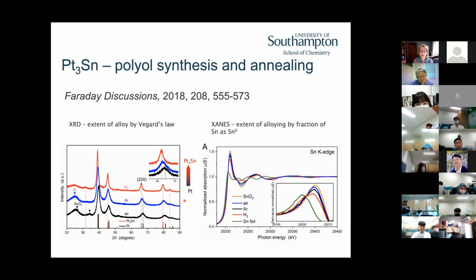If we anneal it in air, argon, or hydrogen, what we do is we exchange the extent of mixing of the materials and of the atoms in the nanoparticles, such that if you anneal them in air, the sample looks very much like a platinum sample in terms of diffraction. When you anneal them in hydrogen, you really mix the materials and you get the platinum 3 tin that you'd expect. You see the peak shifting, and that allows you to calculate the extent of alloying using Vegard's law.